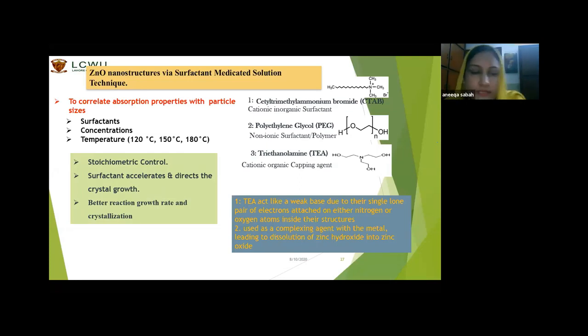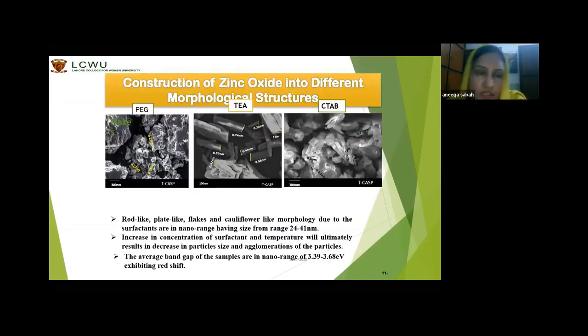We got this kind of structure with PEG, polyethylene glycol: rods and whiskers, rod-like, plate-like flakes, and cauliflower-like morphology due to the surfactants, in the nano range, having a size range from 24 to 41 nanometers.